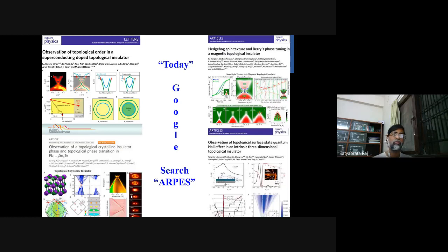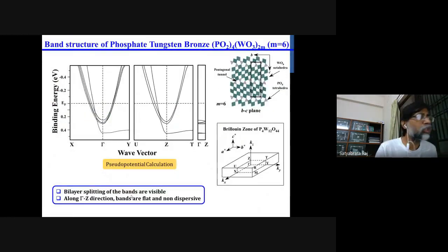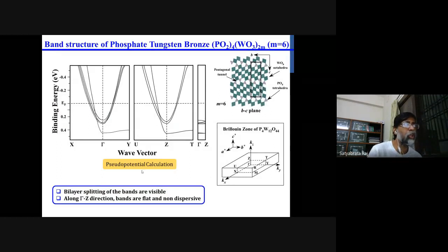So I have taken a band calculation, a pseudopotential calculation, for this system, and because of this 2 layer, this is 1 layer and this is another, you can see the calculation picked up the bilayer splitting. And along the gamma-Z direction, you can see very little dispersion. There is no dispersion along gamma-Z. So that is why these are 2-dimensional systems.